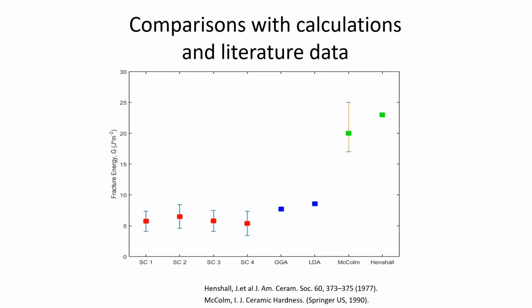So what it seems here is we're actually getting quite a good measurement of the surface energy of a single crystal of silicon carbide. That's quite interesting from a point that goes right back to where you would start off thinking about fracture mechanics and how Griffith thought about fracture mechanics. It actually supports that initial idea, but it also means that we should be sensitive to changes in chemistry of any interfaces we then go on to measure. So all we're really doing here is we're measuring the energy to break those bonds down that plane, and we don't have any other dissipation mechanisms.